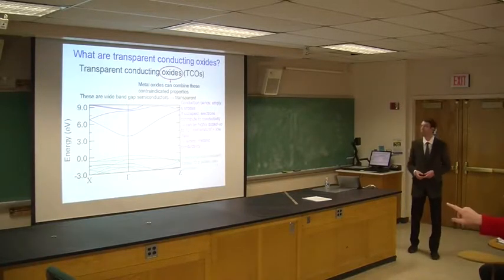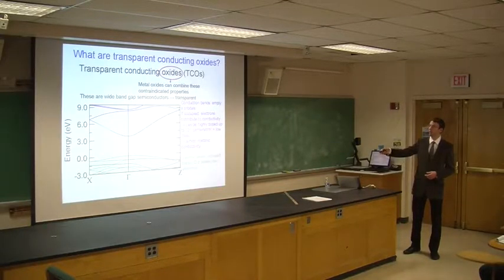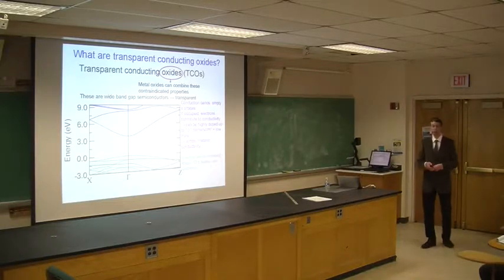Yes? So for good conductivity, you want the bands to be flat? No, you want them to be curved. Yeah, because it's related to the effective mass. So the more curved the bands are, the smaller your effective mass, the easier the electrons move in your material. But it's a good point.